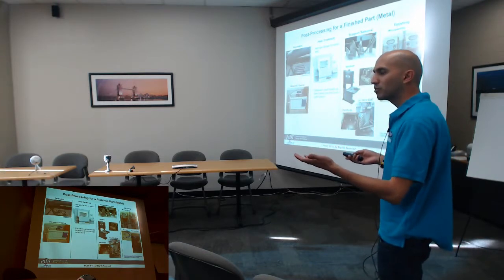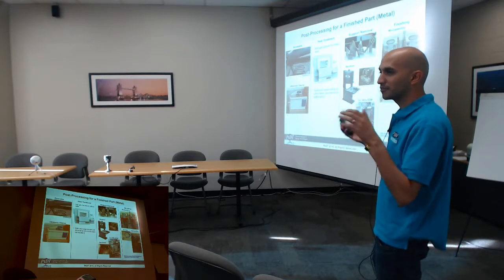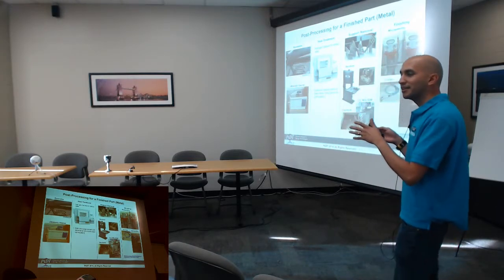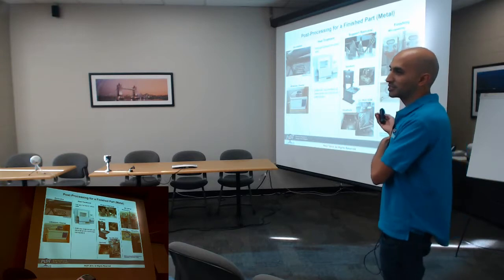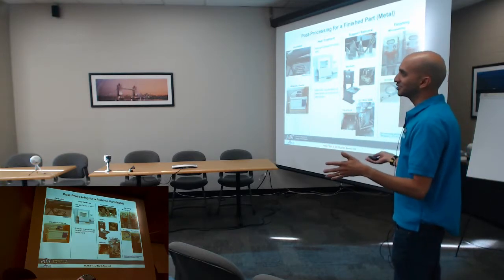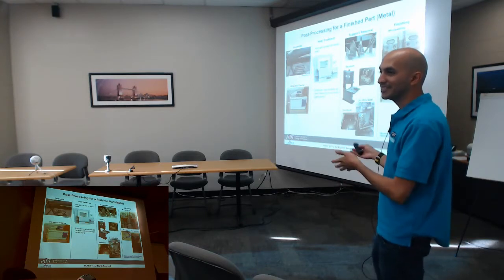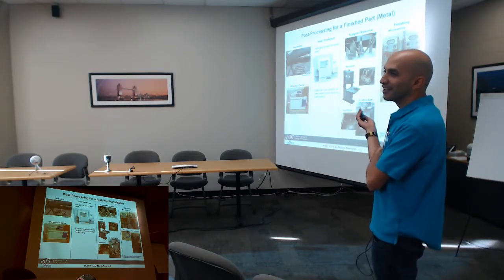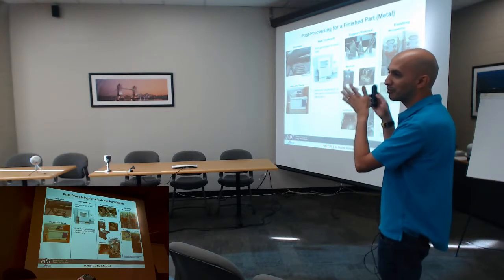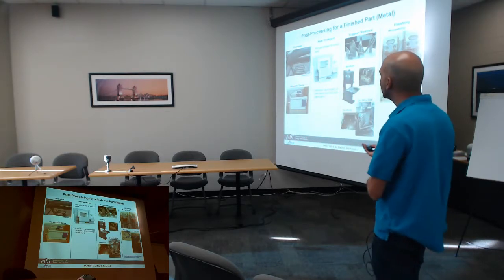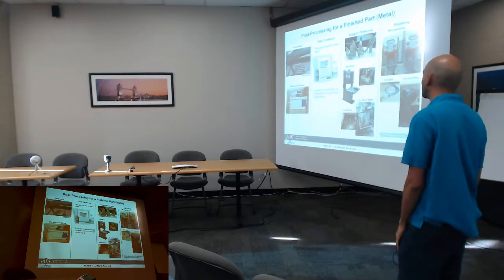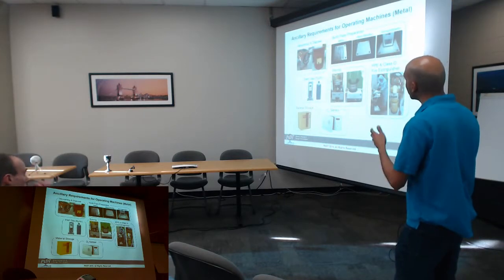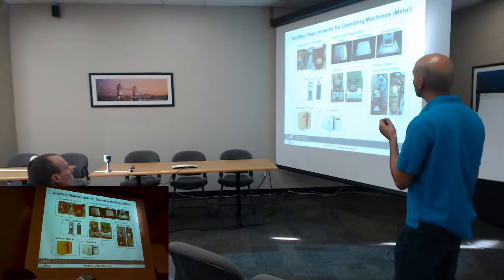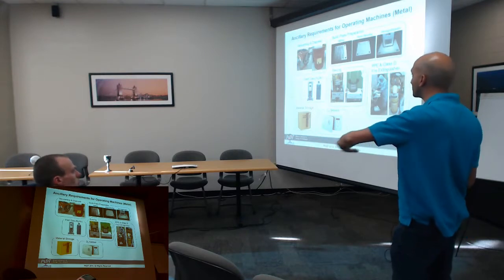The rule of thumb people quote is that material cost is half of the total cost. You can double that, and that's all my post-processing cost. Or the other joke is for large aerospace companies, it takes 3 days to print a part and 30 days or 3 months to finish it. And I haven't spoken about inspection, I haven't spoken about machining true parts. So there's a lot of back-end work, so the part's not printed and ready to go, unfortunately. And I touched upon safety, but there's all these other things you will see in the room. You have to prepare a build plate each time. It has to have a certain surface roughness for that first layer.